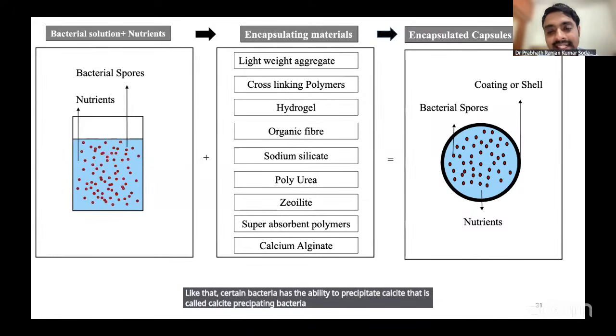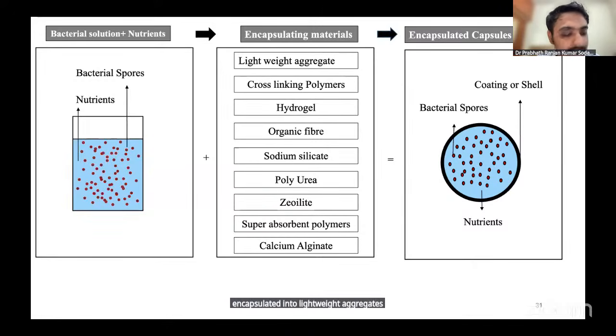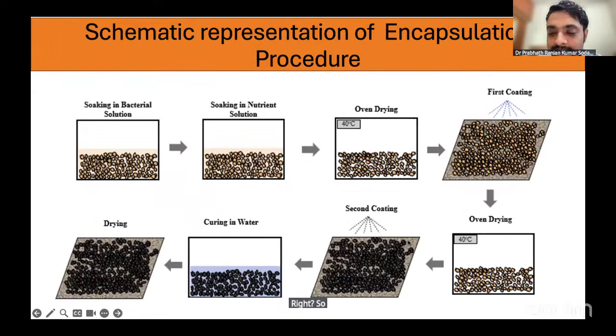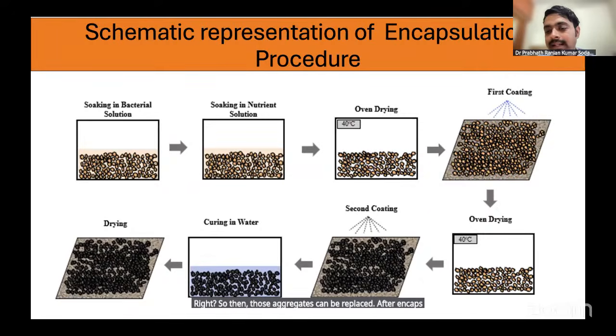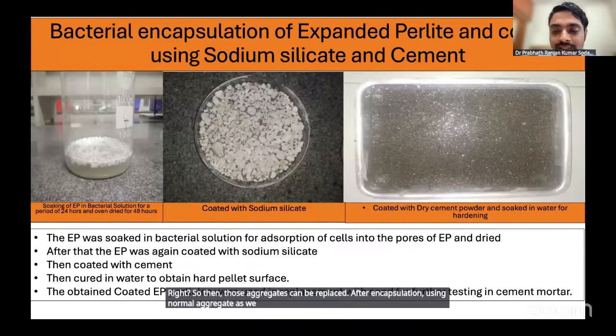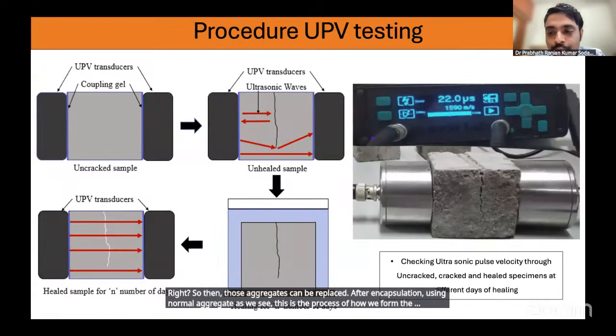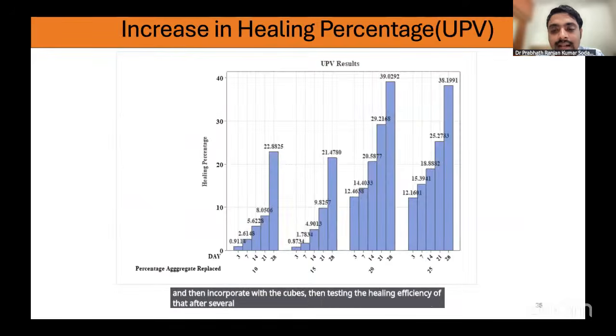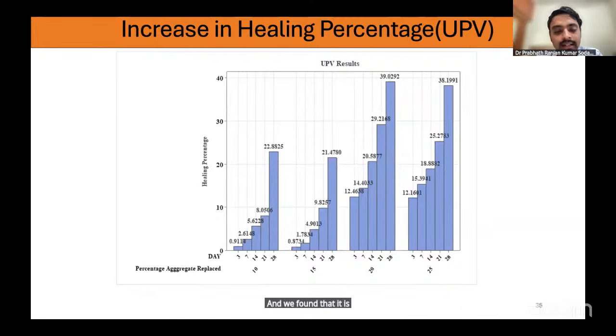That can be encapsulated into lightweight aggregates or polymers or specific things, right? Then those aggregates, after encapsulation, can replace normal aggregate. As we see, this is the process of how we form the aggregate, and then incorporate it into the cubes, then test the healing efficiency after several days and at several concentrations. And we found that the healing was around 39% higher when compared to